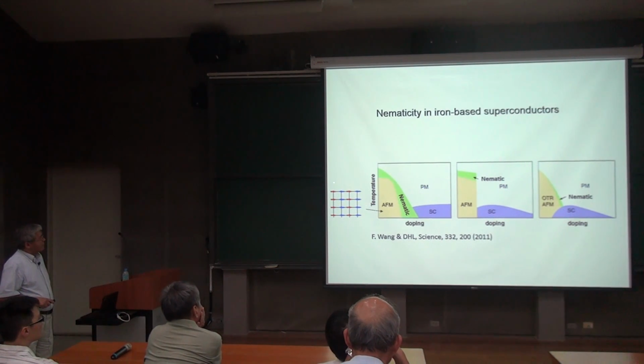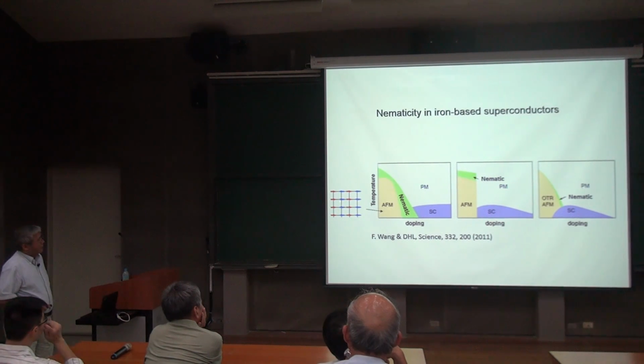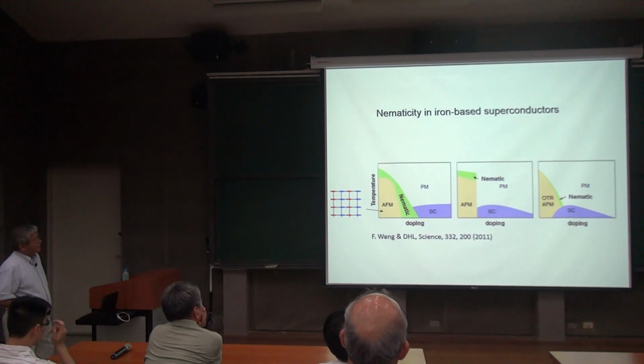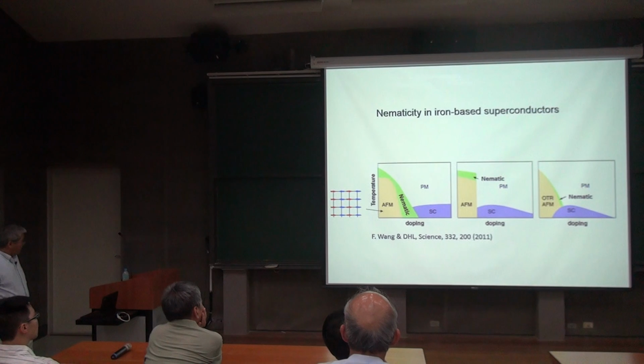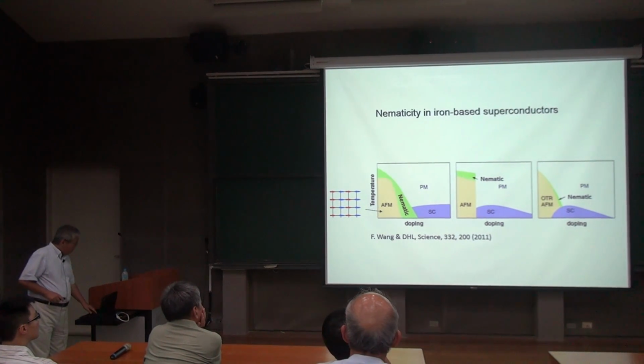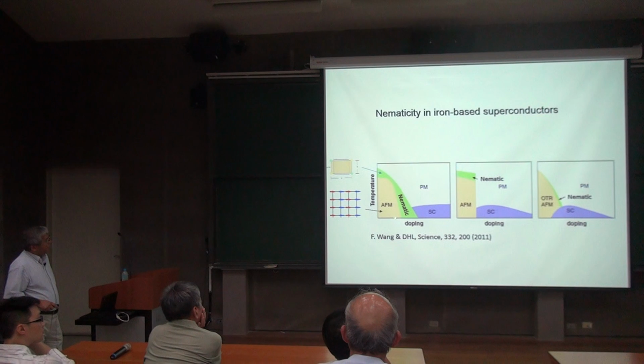If you look at this pattern closely, you will find that the magnetic moment aligns, in this case, in the vertical direction, but anti-aligns in the horizontal direction. This type of magnetic pattern is called a stripe magnetic pattern because it consists of ferromagnetic stripes aligned antiferromagnetically. If you raise the temperature, for example, let's say we fix the doping and raise the temperature and cut through the phase diagram like this, you will find that this antiferromagnetic order is destroyed in this green region.